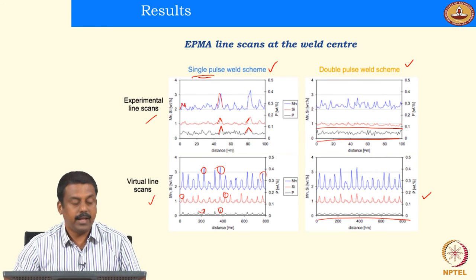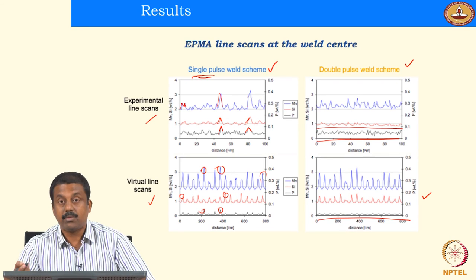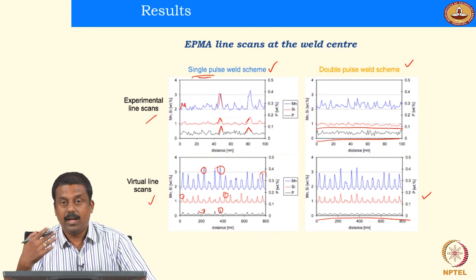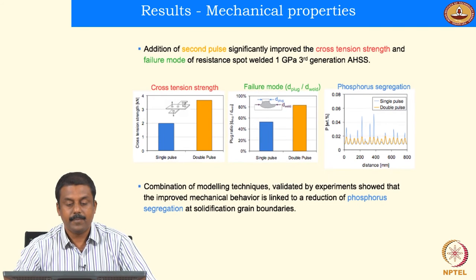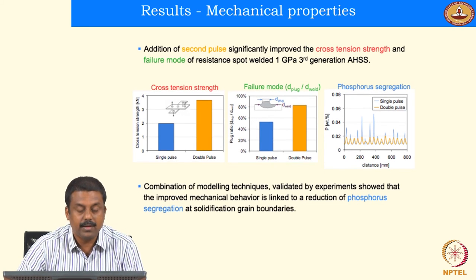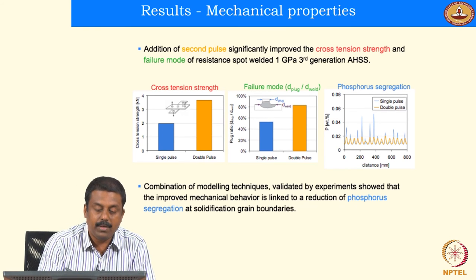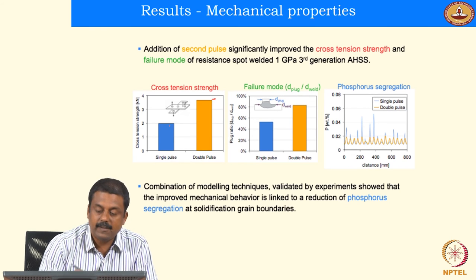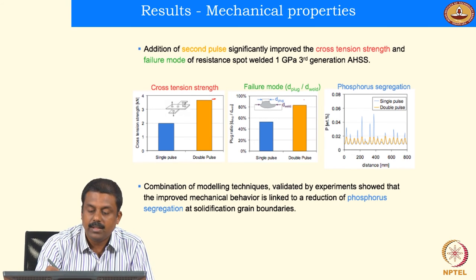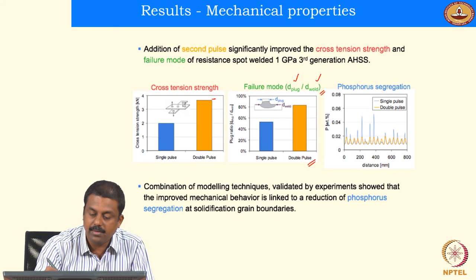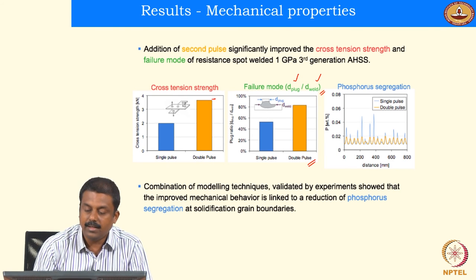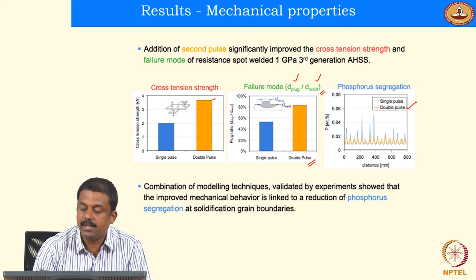That means that the second pulse helps in avoiding the segregation of phosphorus particularly, which is actually very beneficial. If you do not have phosphorus segregation, your embrittlement decreases significantly. The results of the cross tension test we already showed in the previous slide. After double pulsing the strength is increasing compared to the single pulse case, and also the failure mode, the plug ratio. What is plug ratio? Again, recall from my previous lectures, the size of the plug after the testing divided by the size of the weld nugget. After the double pulsing, the plug ratio is also increasing significantly. Okay, and that is mainly due to the reduction of phosphorus segregation after double pulsing.